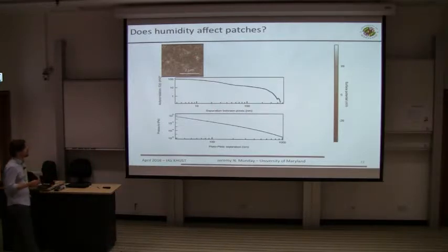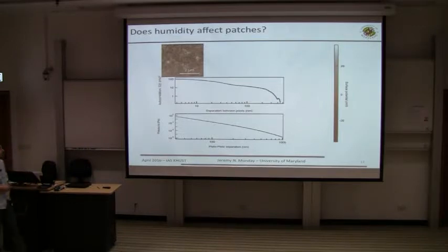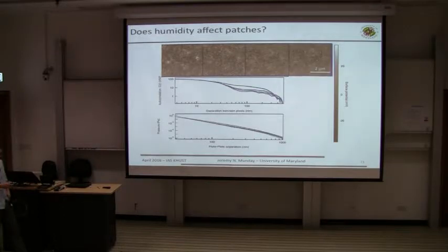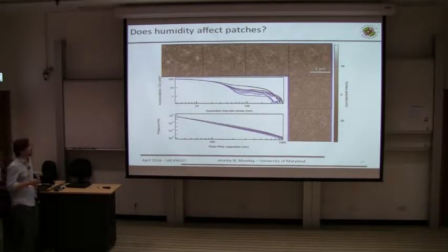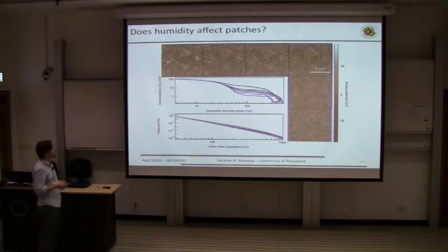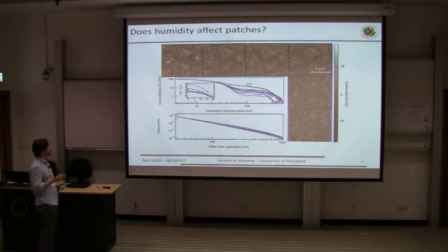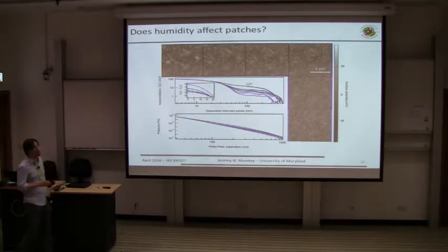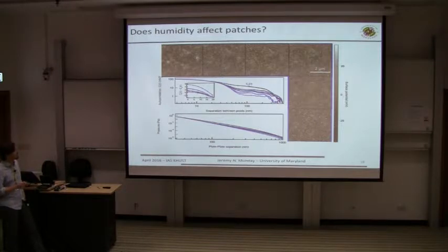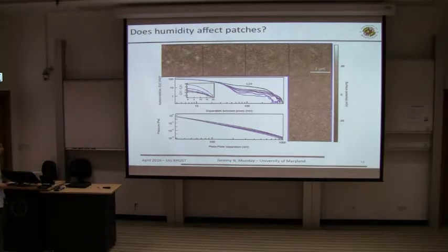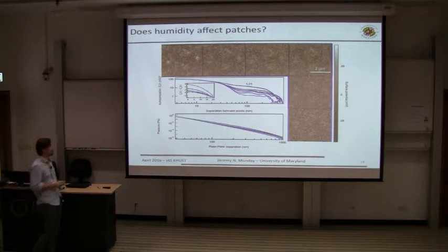And so basically you're going to use this function in order to determine what the electrostatic force would be based on patch potentials. And then as we start decreasing the humidity here, we see that the patches start to change. And so there's a change in the long wavelength range. There's also a change in the short wavelength, sorry, not wavelength, the separation region here. And they're actually kind of counter to each other. And so they affect the force in different ways. But you have to go through all of it in order to determine what the actual effect is for the samples. So that's something else that we're keeping in mind as we continue on with this.